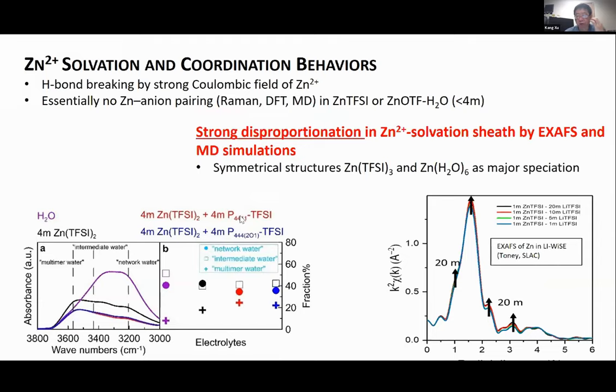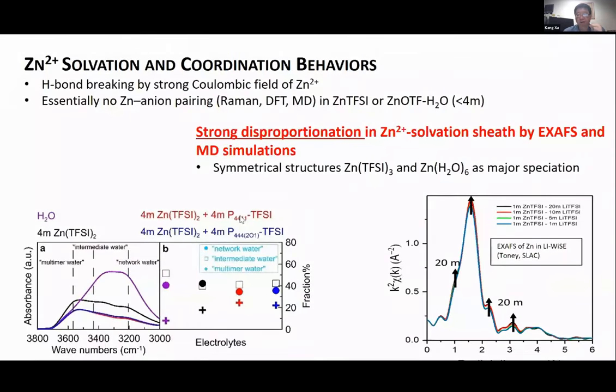Because of the strong coulombic field of the zinc cation, the water hydrogen bond network is completely disrupted, as revealed by the FTIR. You can see that there's almost no free water existing, even at very low concentration, and up to high concentration the water network is completely disrupted. And by doing experiments and modeling to support the interpretation of the data, we found that zinc strongly prefers a symmetric solvation structure. So what does that mean?